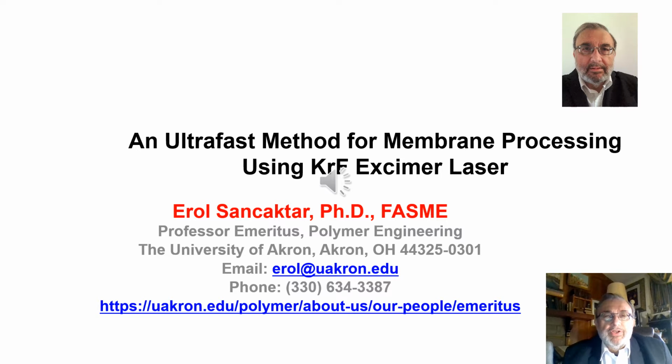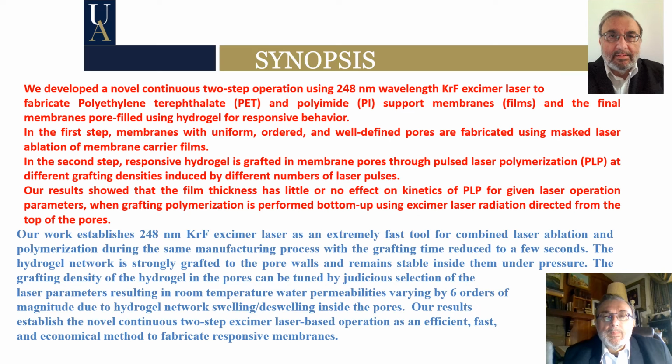My presentation is on an ultrafast method for membrane processing using a krypton fluoride excimer laser. Let me first present a synopsis. We developed a novel continuous two-step operation using a 248 nanometer wavelength krypton fluoride excimer laser to fabricate polyethylene terephthalate and polyimide support membranes, and the final membrane pores are filled using hydrogel for responsive behavior.